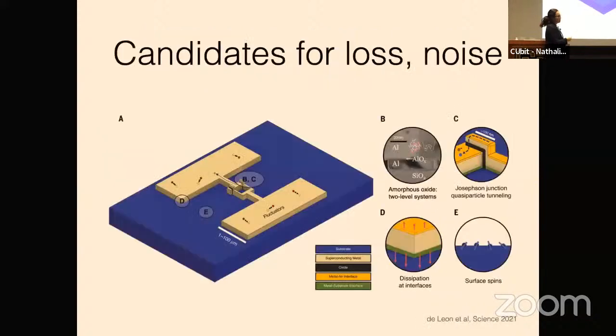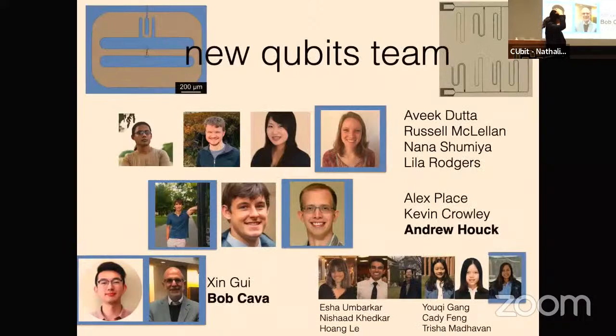There's a number of candidates for this loss and noise if you just kind of stare at a transmon. You have the substrate surface, and you have the device surface, and you have kind of funny physics that can go on in this Josephson junction. So one question is, how do we zero in on where this loss is actually coming from and which surfaces are important? I ran around giving this NV talk for a few years about how we systematically figured out what was going on at the diamond surface and how to improve NV centers.